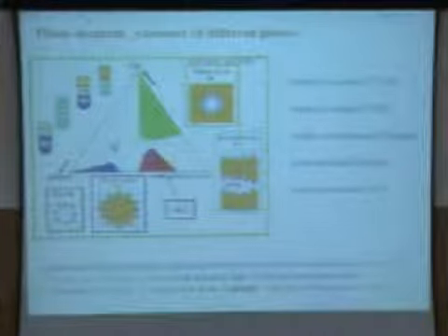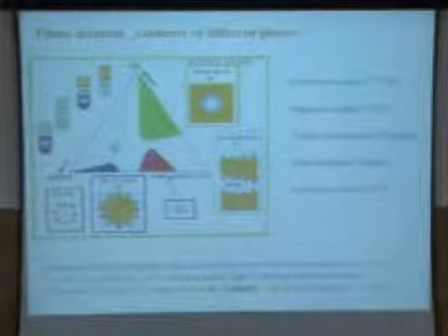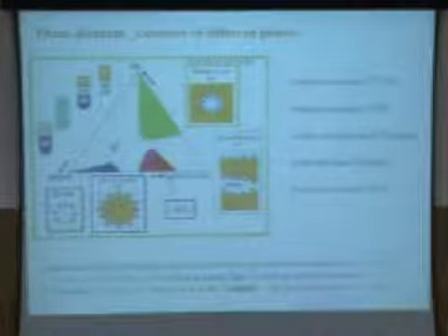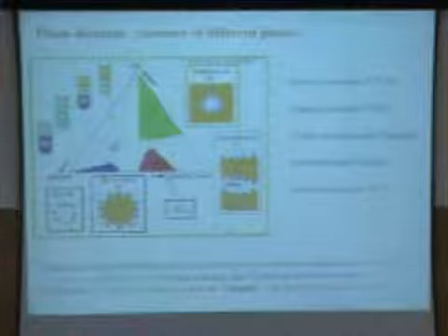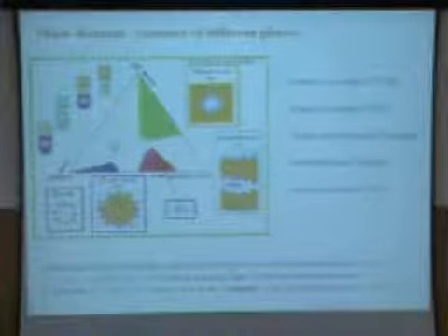Once you want to work with the micelles, it may be possible that you are not getting the right concentration, so you are in a different part of the phase diagram, because you have three different reagents. You have a ternary phase diagram, and you have to understand which portion of that will give you the reverse micelle. Okay? So what you do is you work with different systems, and you generate a phase diagram and map out which part of the phase diagram actually gives rise to what kind of structure. Okay, so once you know that, then you work with that composition.